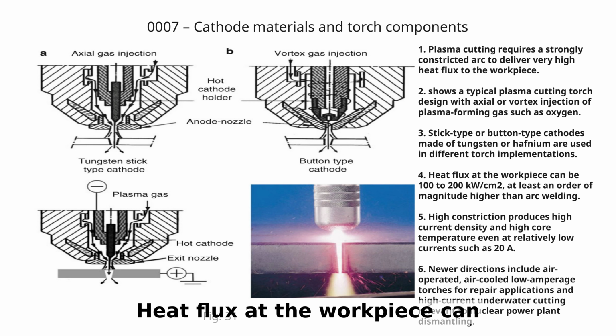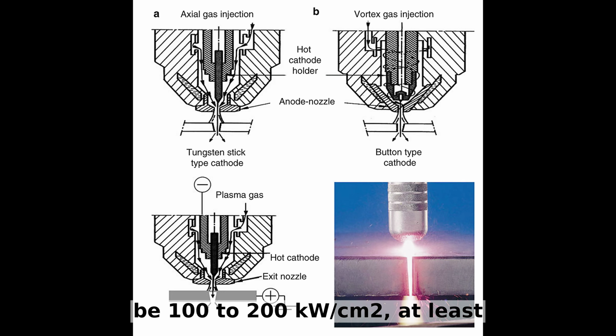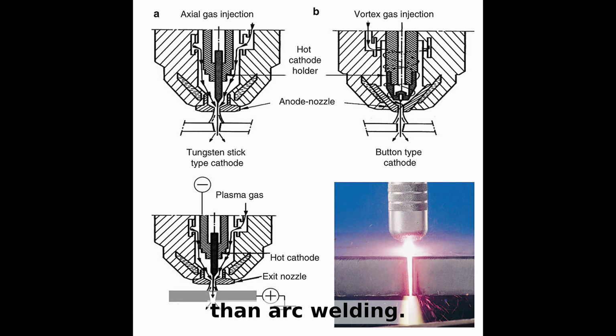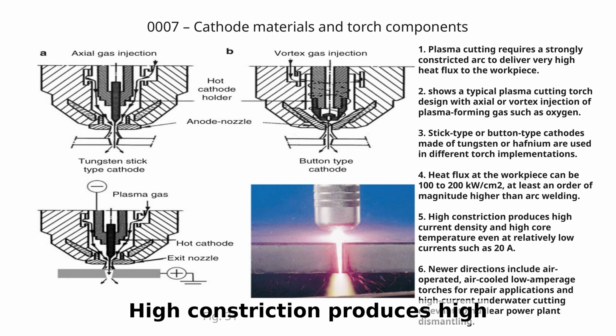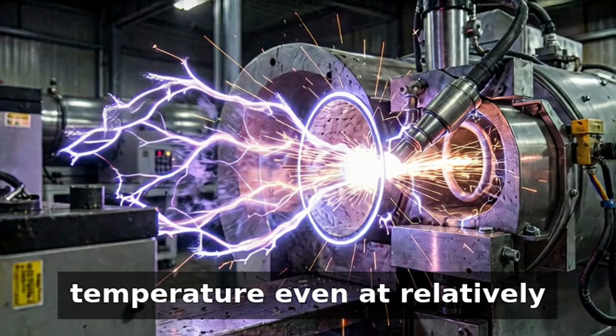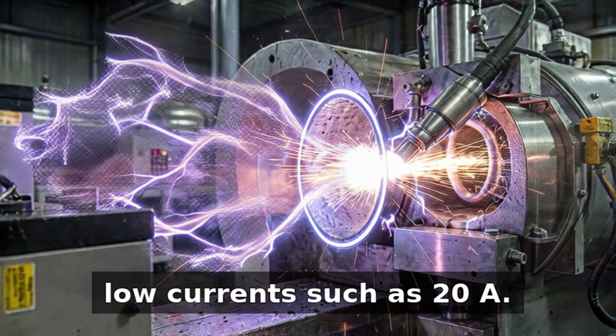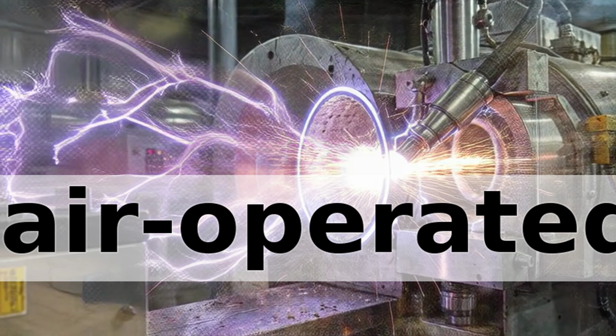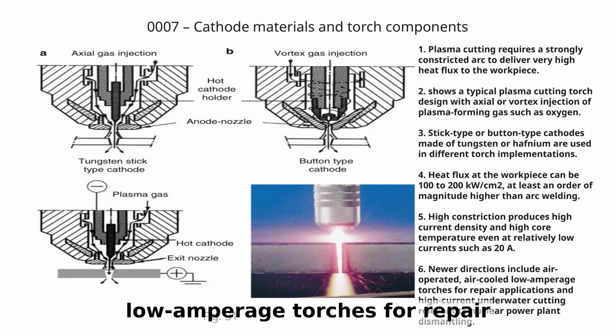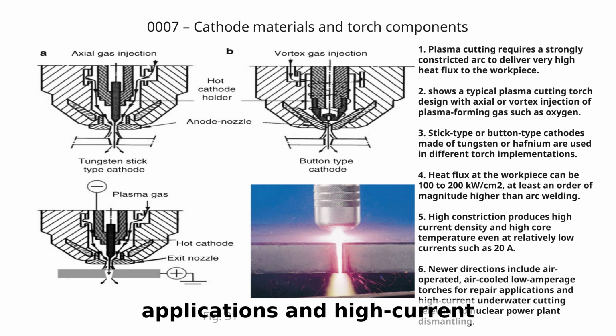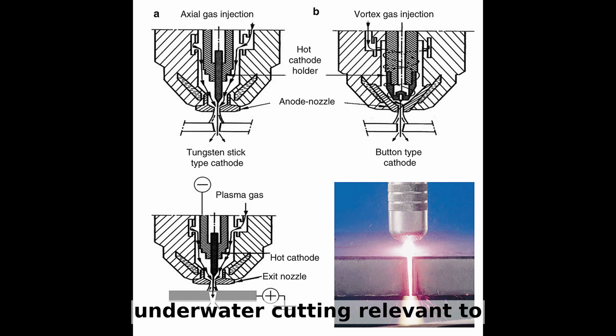Heat flux at the workpiece can be 100 to 200 kilowatts/cm2, at least an order of magnitude higher than arc welding. High constriction produces high current density and high core temperature even at relatively low currents such as 20 A. Newer directions include air-operated, air-cooled low-amperage torches for repair applications and high-current underwater cutting relevant to nuclear power plant dismantling.